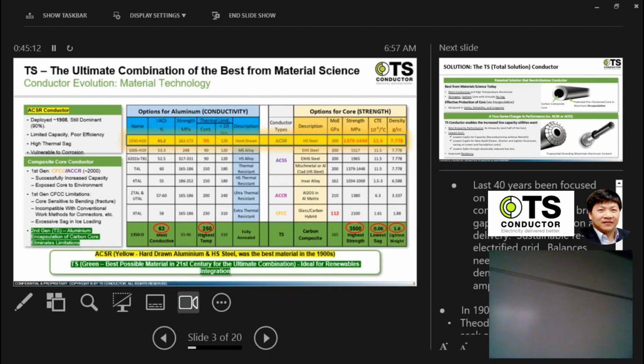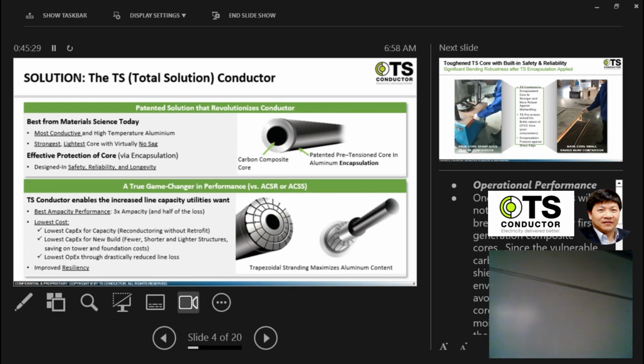What we do in TS is we combine the best in the strength member side, which is the carbon composite, and the best from the aluminum, that's the annealed aluminum. That's how we develop TS. And you may say that you are having the best DNA, quote unquote, in the material combination, but that is no guarantee that you have a great conductor. The issues that we talked about associated with the other type of advanced conductor, we have to address them. Especially the protection against bending failure, the protection for the vulnerable organic constituent in the conductor, and compatibility with traditional work practice. These are things that we have to address.